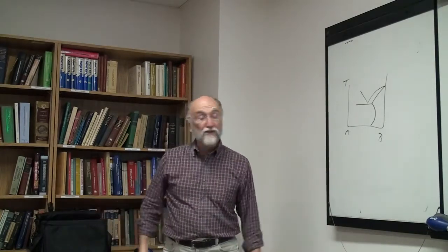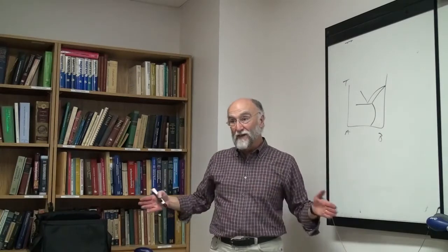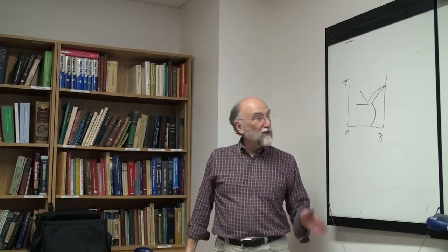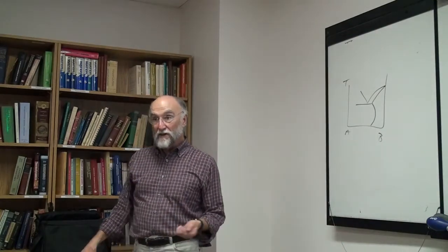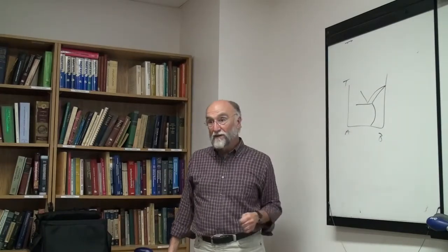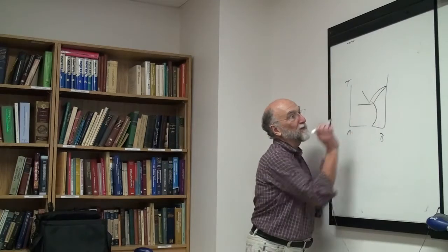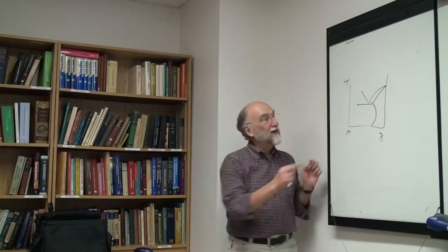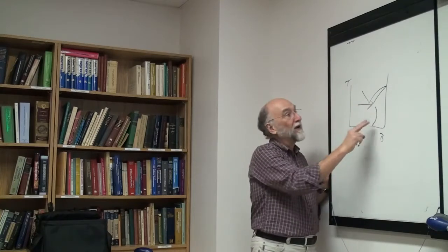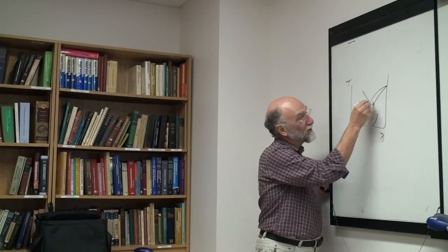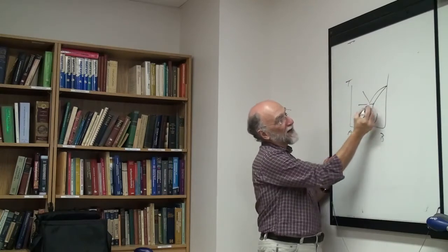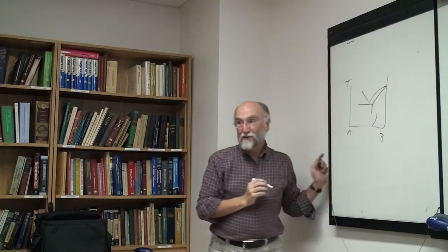There are physical reasons: as you get to lower and lower temperature, the entropy becomes less and less important. It's generally the entropy that's making things soluble, and it's the heat that's making them insoluble. So as you lower the temperature, it becomes less and less soluble, as the energy effect becomes more important relative to the entropy, the disorder, but it doesn't have to be. There are cases that actually go around like that. This, however, still has to extrapolate into there. It can't start out like this. It could even start out with a negative slope, as long as it extrapolates into there.